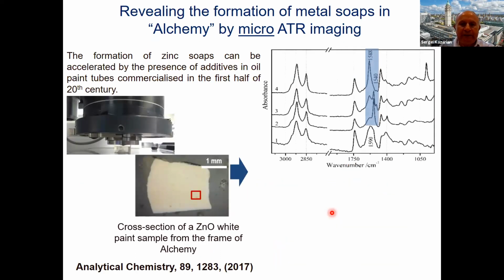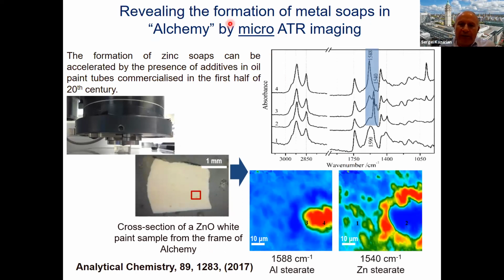In this case, I would like to show you results of samples removed from a real painting, actually from some small droplets on the frame of Alchemy. And what was remarkable is that apart from zinc oxide converting to zinc soap carboxylate, we were able to see that it happens around aluminum stearate, which was also added to the painting at that time. And this basically shed light on why this painting was rapidly degrading.